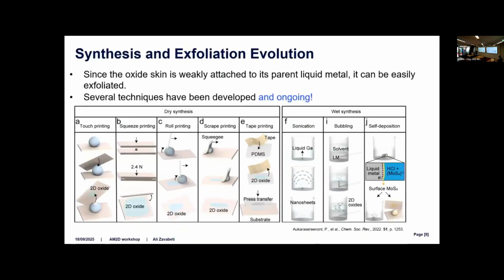So we have invented several methods for printing these 2D oxides. We started in 2016, 2017 with just touch printing: basically, melt the liquid metal on a substrate, get another substrate, touch the surface and delaminate. So we could harvest 2D layers.